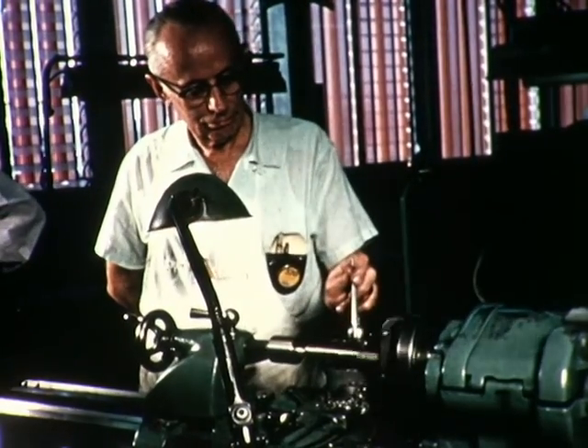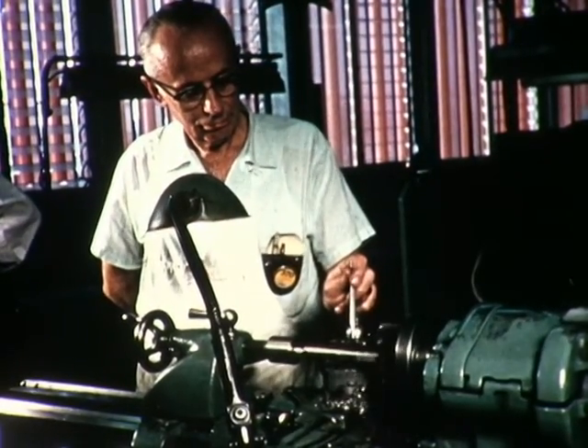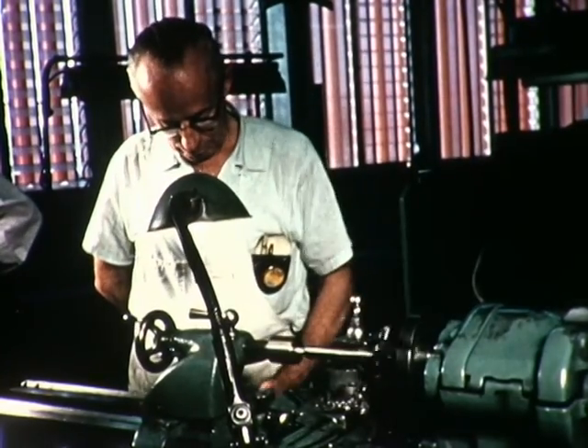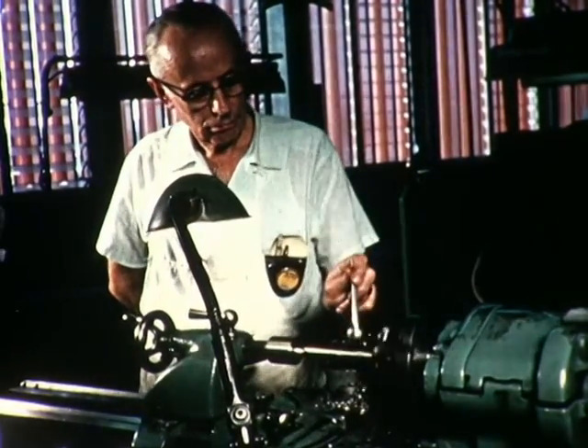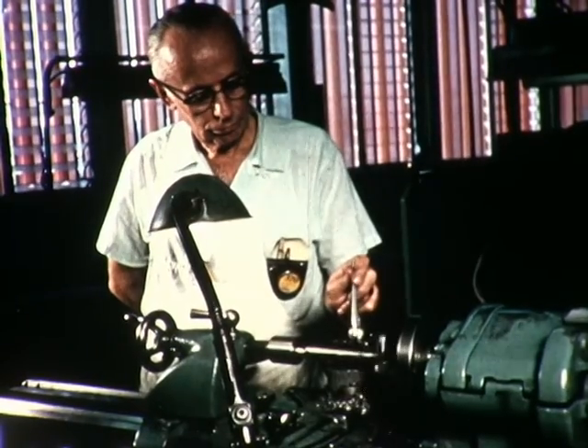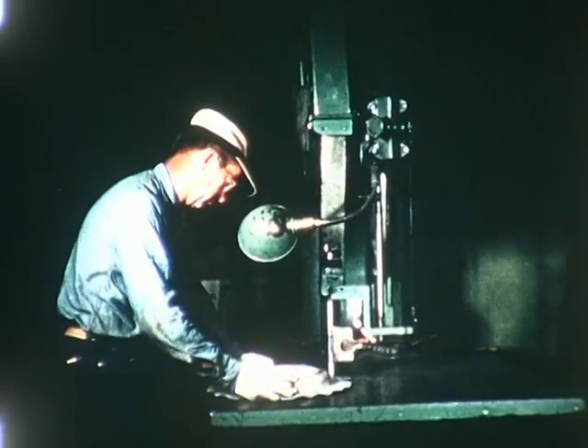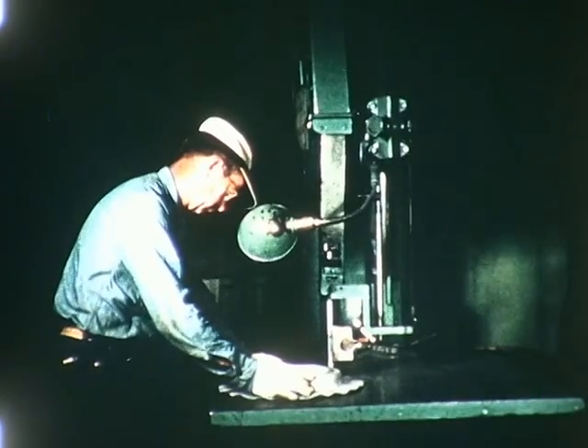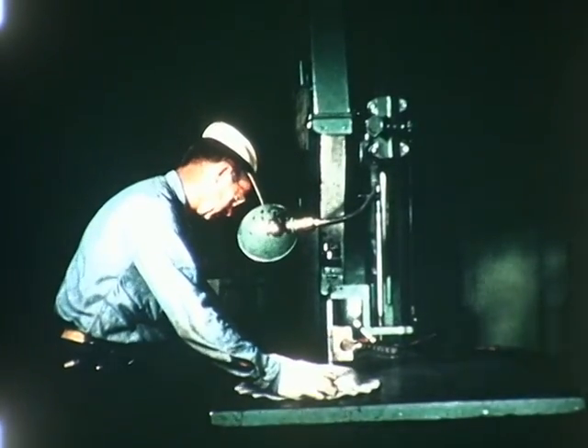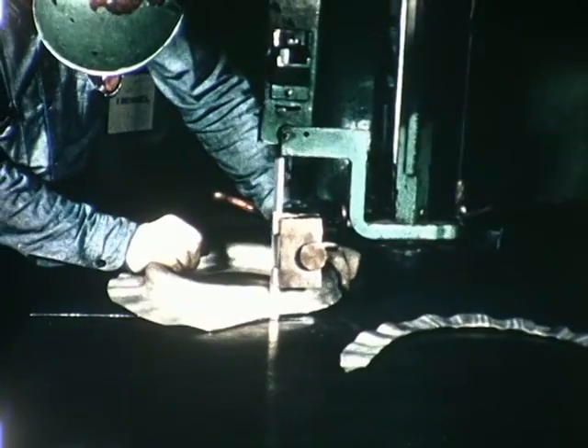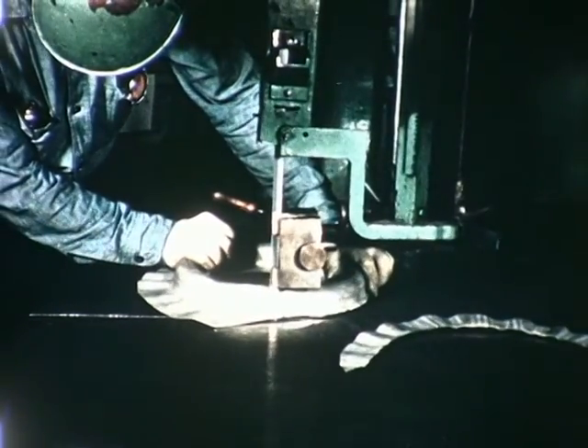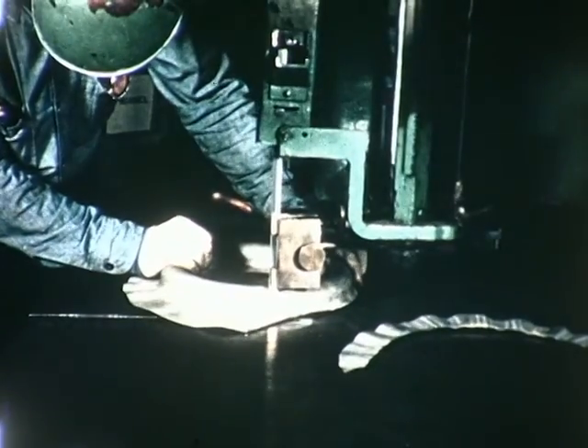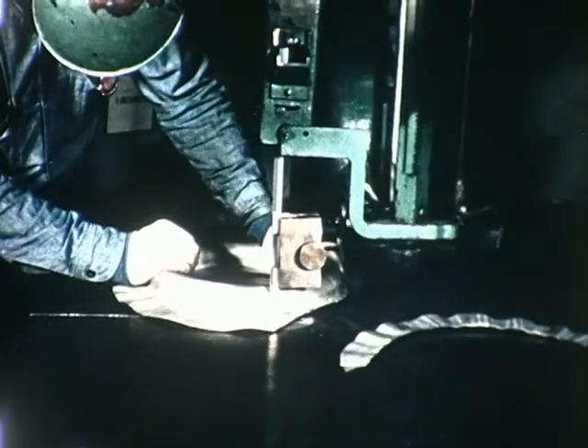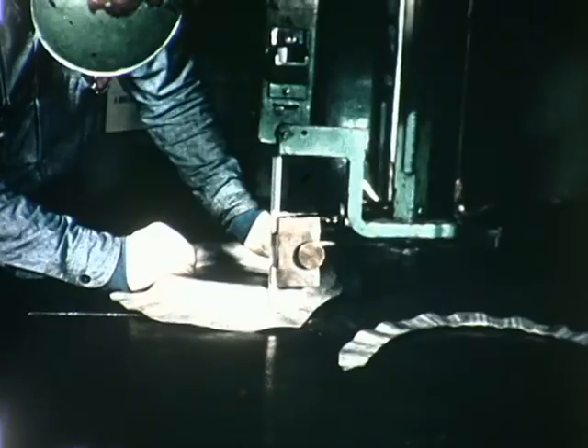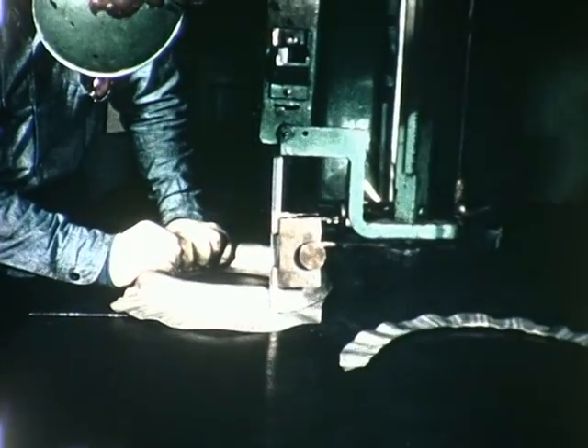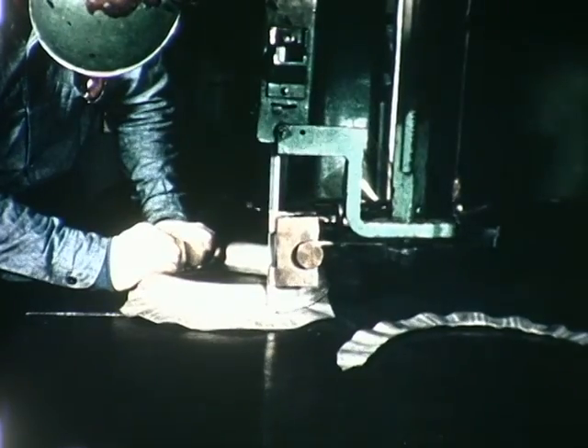Rene 41 may be machined without difficulty, even though it is less machinable than Inconel X. The use of high-speed tool steel in machining operations seems to have advantages over carbide tip cutters. Rene 41 does not saw readily on do-all or slow-speed saws. Cutting may be accomplished on high-speed saws, such as the Tannewitz, which cuts by a friction process. Square shears or rotary shears may be used, similar to 18/8 stainless. The material cannot be cut with a hole saw, and all holes must be drilled or punched.